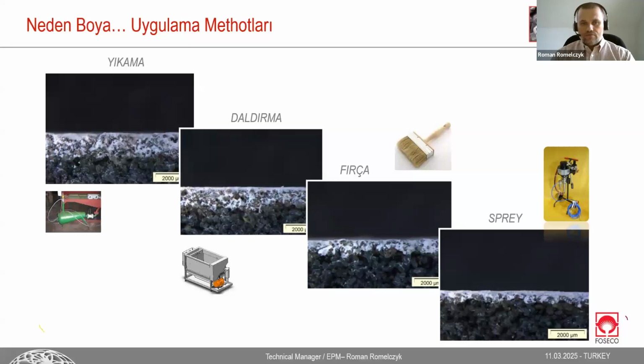It's around 12, 13, 14 seconds. When we talk about brushing, it's around 18, 20. It depends what kind of raw materials are used for the coating. When we talk about zircon, which is roundish in shape, it's quite easy to brush. If we talk about olivine or magnesite, it's not that easy for brushing. This is why we need to dilute more. So it will be some kind of 18 seconds, measured by a DIN cup with a 4 millimeter nozzle.